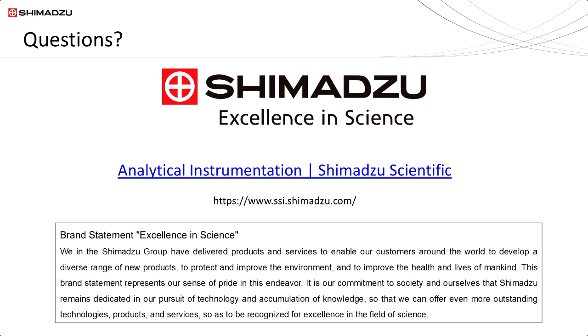For example, if the sample has a lot of salt, the salt can deposit on the cones of the ICP-MS and affect your analysis results. But ICP-OES has much better sample tolerance. It can measure high salt samples with very high total dissolved solids, up to 40%. So if ICP-OES could not reach the detection limit you require, then it might be a good time to consider ICP-MS. But if ICP-OES can get to the detection limit you require, then I will stick to the ICP-OES.